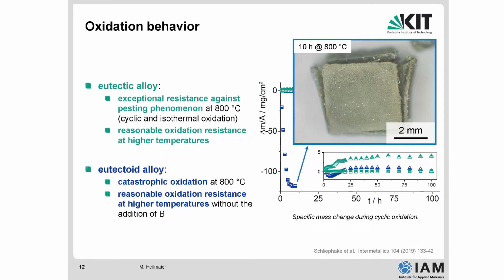And this dramatic weight loss is exactly what I meant with molybdenum oxide sublimation or volatile molybdenum trioxide species. This is how the material looks like at 800 C after 10 hours already. You see that the oxide scale does not adhere, it spalls off. The oxidation goes on rapidly. You form this yellow shiny oxide here on the scale. In other words, we call this alloy not oxidation resistant. It causes catastrophic oxidation at 800 C, so you would never use this alloy at elevated temperatures.